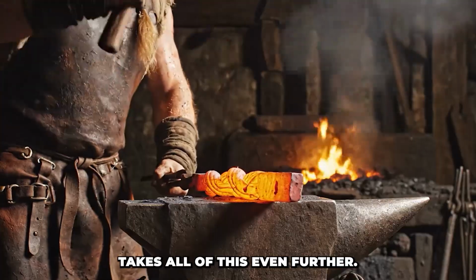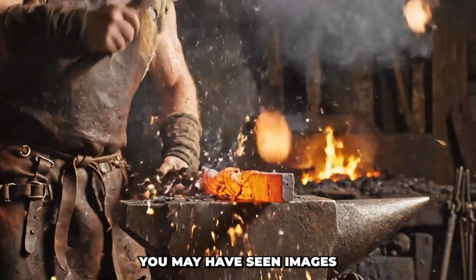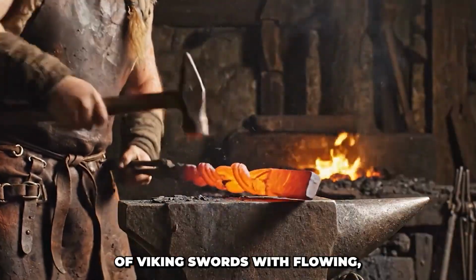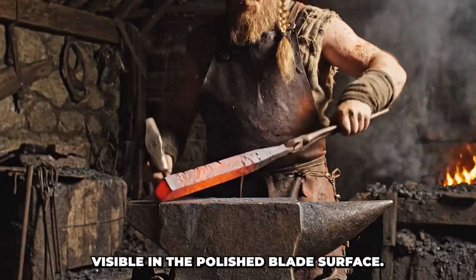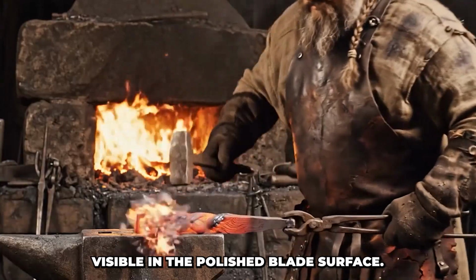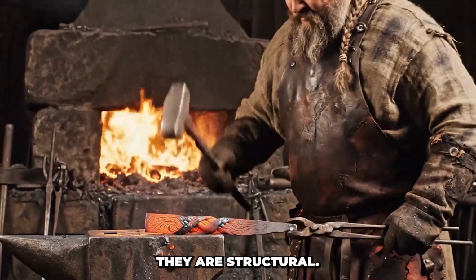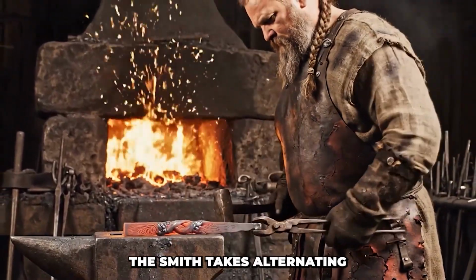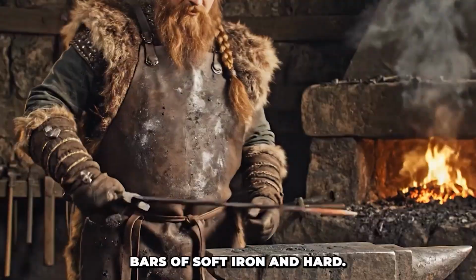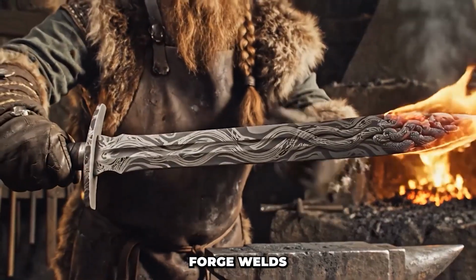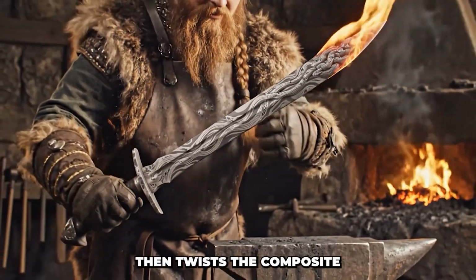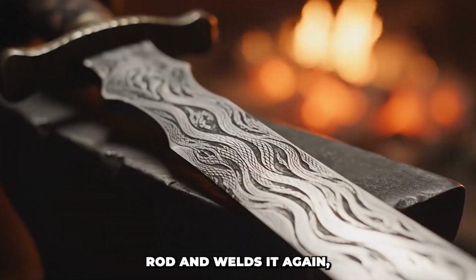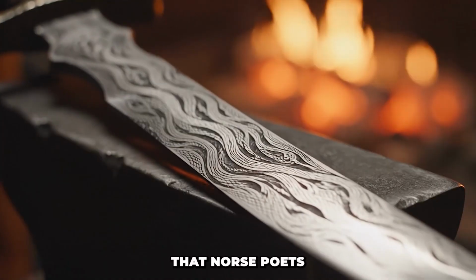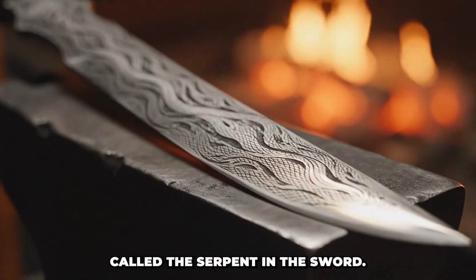Pattern welding takes all of this even further. You may have seen images of Viking swords with flowing, almost organic patterns visible in the polished blade surface. Those are not decorative, they are structural. The smith takes alternating bars of soft iron and harder carburized steel, forge welds them together, then twists the composite rod and welds it again, building up a layered structure that Norse poets called the serpent in the sword.